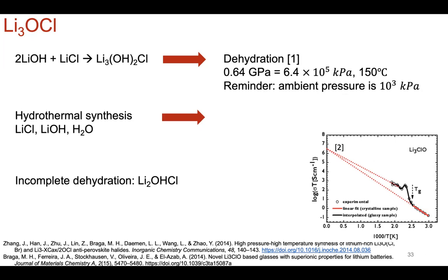These types of compounds, dehydration is really the key processing step. And when done not carefully, what you end up really measuring is the ionic conductivity of the hydrated phase, which is not what you're intending to do, right? So some studies have tried to dehydrate at very high pressure. So I list our ambient pressure here to give you a sense of how high these pressures have to be at 0.64 gigapascal. So that's 2 orders of magnitude greater than our ambient pressure. 150 C is not that high, but the pressure is pretty